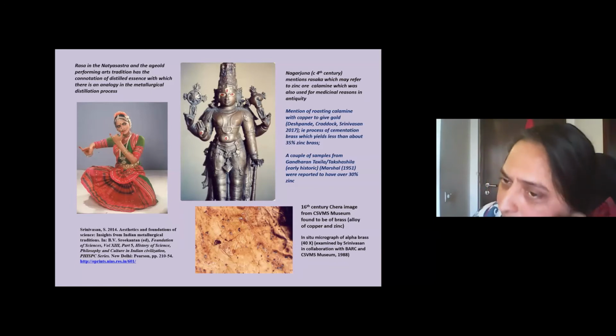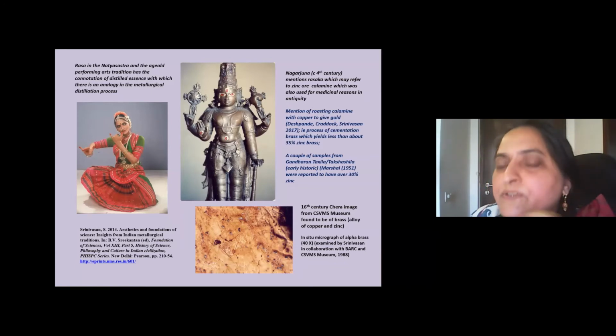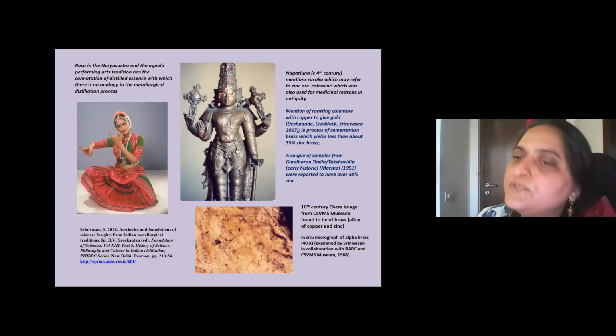So there was also a shloka mentioned, and that is also what I'm pointing to here, which is translated in Deshpande and mentioned in Craddock and so on, where roasting of calamine along with copper gives the gold. Basically, when you heat the zinc carbonate into zinc oxide, it gets reduced to the vapor, and then the vapor gets into the copper. So it's called a cementation process. So this is what we call cementation brass.